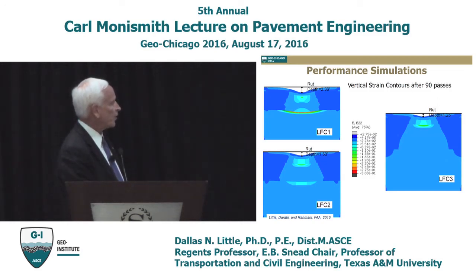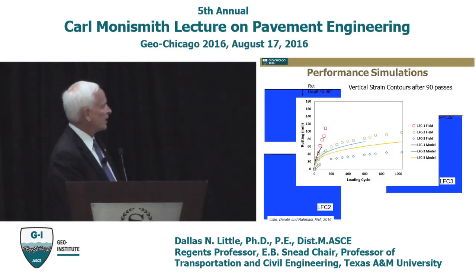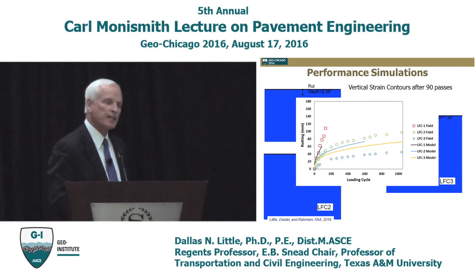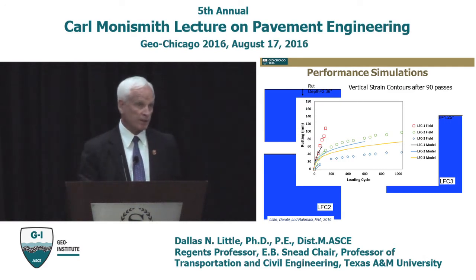And this is the way we were able to predict. We did a really good job in LFC 1. As you can see, the line mimics the data pretty closely. LFC 2, the data are the open circles. The blue line actually is the measured or the model response. And in LFC 3, we weren't quite as good, but we can improve that by 3-dimensional modeling. This was just a 2-dimensional axisymmetric model.